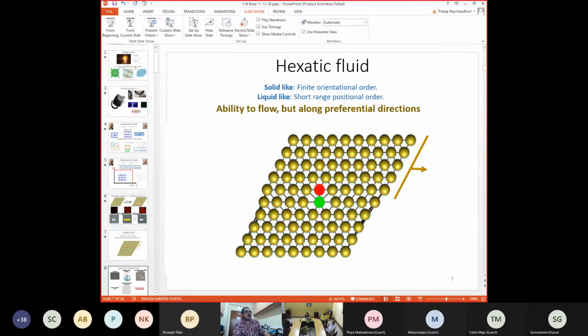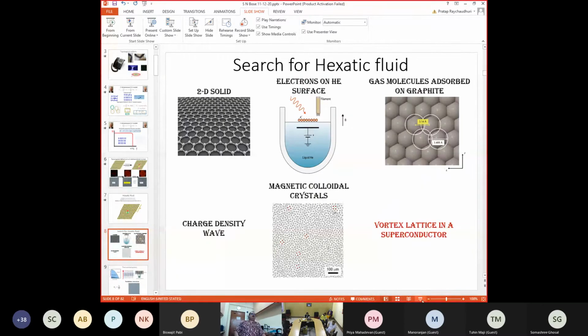Now, given the unique nature of this state, there was a lot of attempt to search for a hexatic fluid. The obvious thing to look at is a 2D solid like graphene, but for obvious reasons that does not work, because if you take a 2-dimensional sheet of, let's say, graphite, there is no reason that it has to be constrained in 2 dimensions. So by the time you heat it and you go even close to the melting, it has buckled up, it has become a nanotube, it has folded, and therefore it's not a 2-dimensional system.